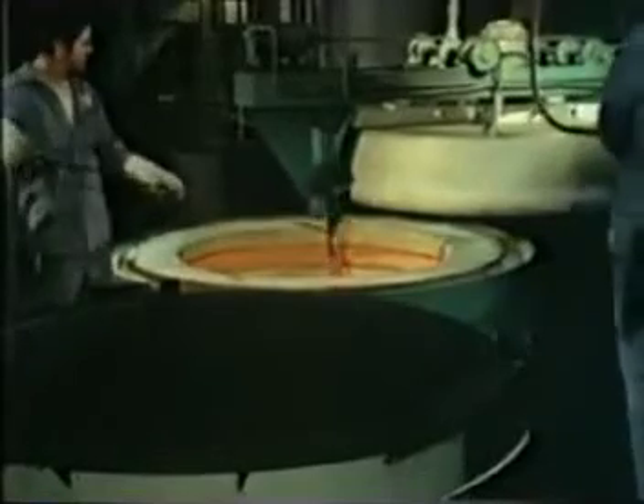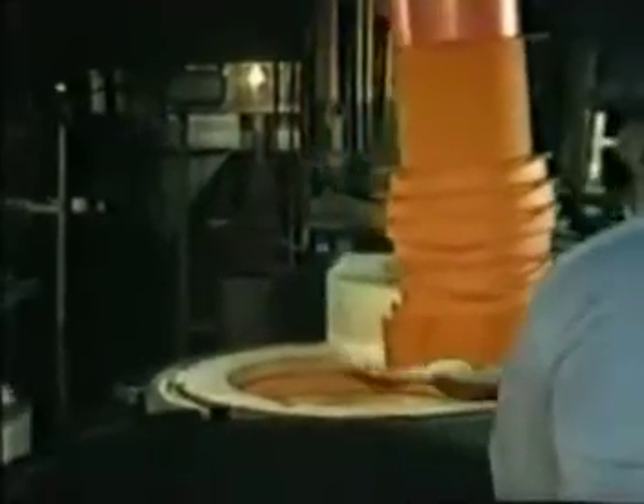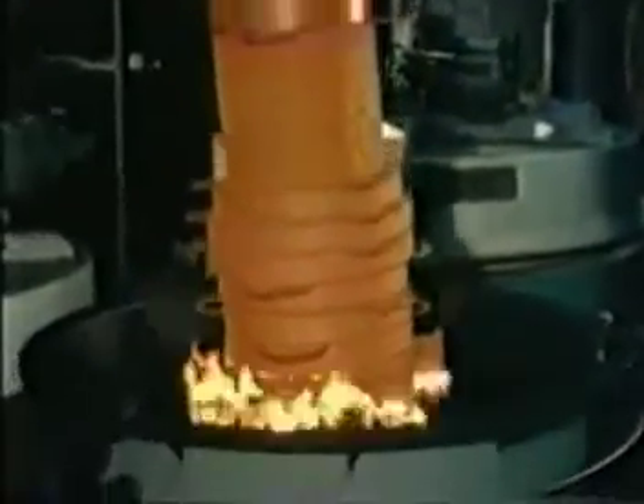An example of batch equipment is the cylindrically shaped pit furnace. In this type of equipment, work to be processed is loaded into a basket or racked on a fixture, and then is transferred to the heating chamber through a top opening lid or door for the required heating cycle. Upon removal from the heating chamber, the batch load is then quenched in a suitable cooling medium. Probably one of the more common types of batch equipment is the radiant tubed integral quench furnace. This furnace is a controlled atmosphere type and has a quench tank incorporated as an integral part of the equipment so that work can be transferred from the furnace to the quench tank without coming out into the air.